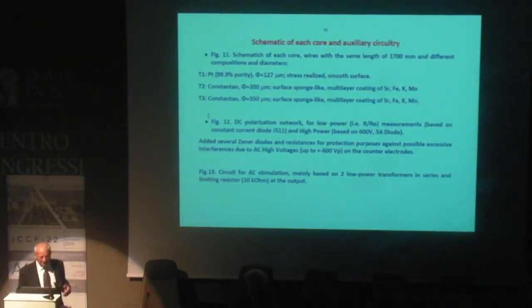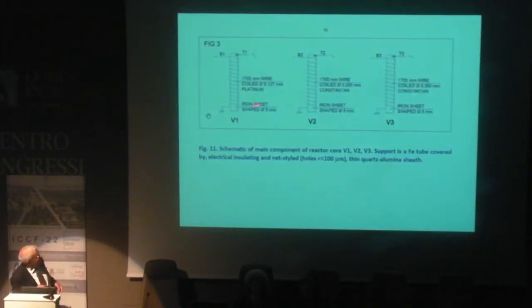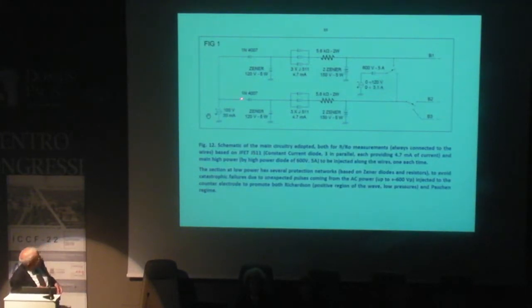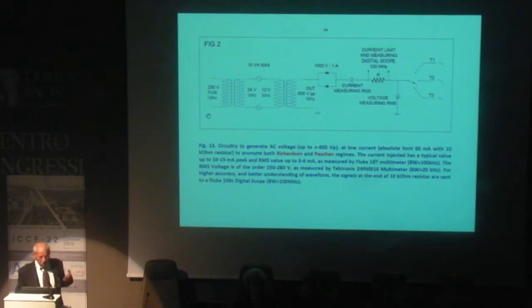Here is a schematic of some auxiliary circuitry, because we use very large voltage and several times we had damage to the electronics. Here's a sketch of the 3 wires, all the same: platinum, constantan 200 microns, constantan 350 microns. This is the auxiliary circuit to measure the resistance ratio of the wires and the protection network, several protection networks. And this is the simple oscillator we built to have a sinusoidal wave up to 600 volts, just using the mains, and we measure the current flowing at the counter electrode through this resistor, voltage and current.